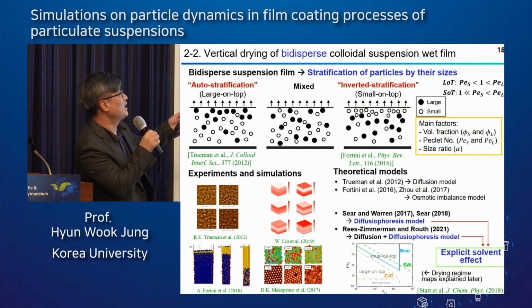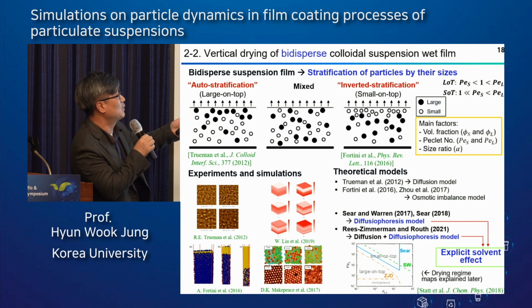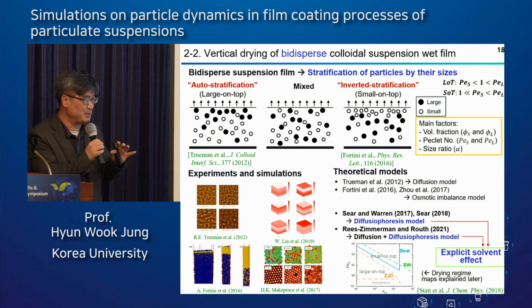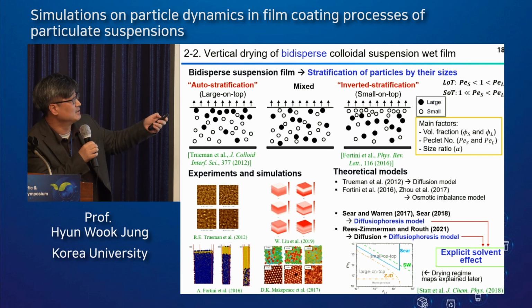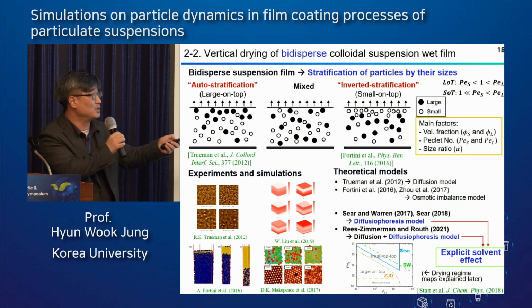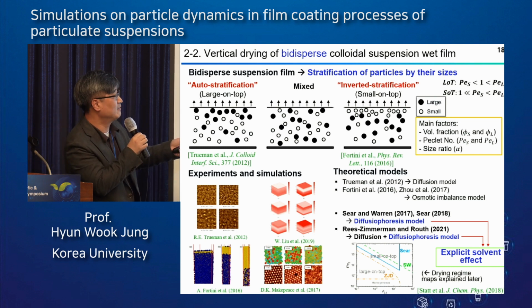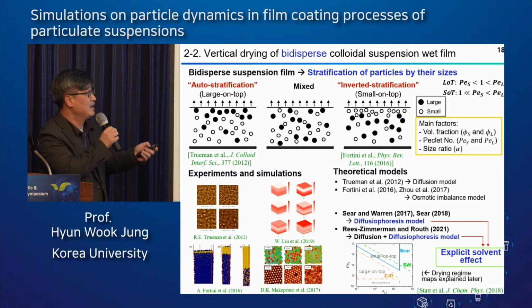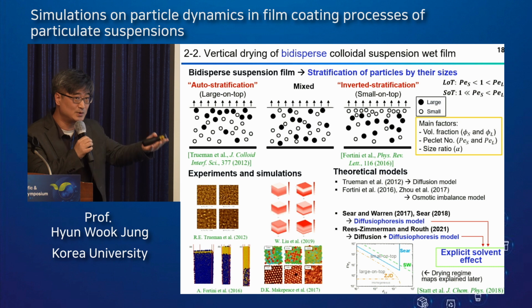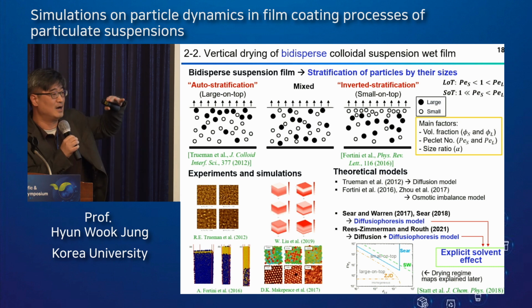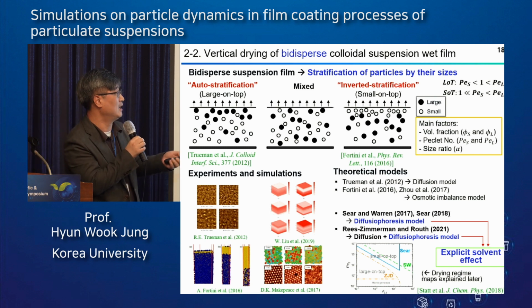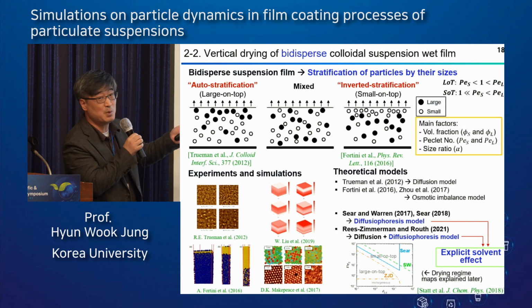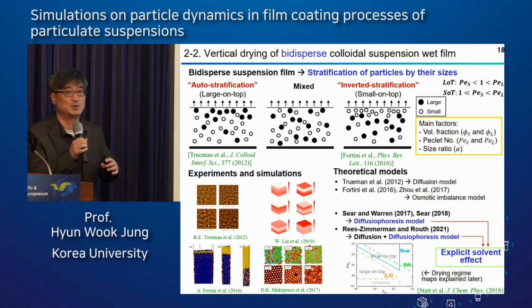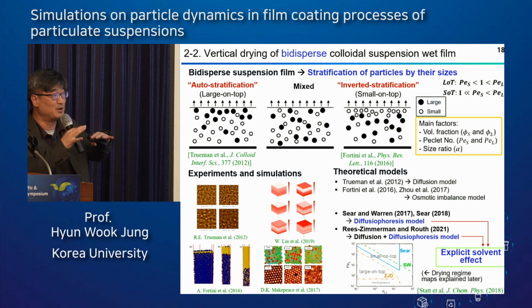The second is drying of a bidisperse colloidal suspension wet film, with large particles and small particles. I think the most important issue in this case is stratification of particles by their sizes, depending on the Peclet number, particle size ratio, and the volume fractions. In general, slow evaporation induces large on top, with the large particles positioned on the top, so-called large-on-top stratification. High evaporation made the small-on-top structure, which we call inverted stratification. So we try to compare this stratification by changing the Peclet number.